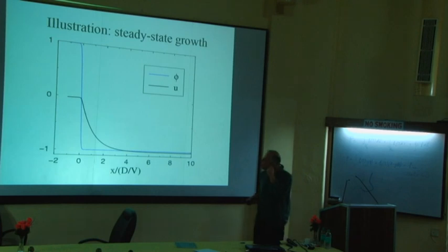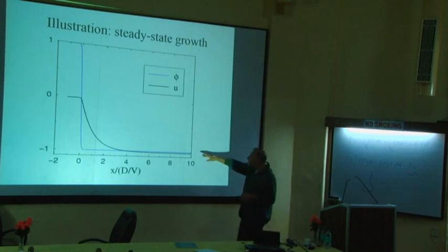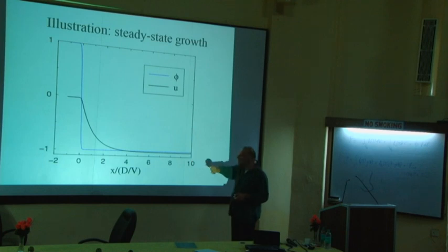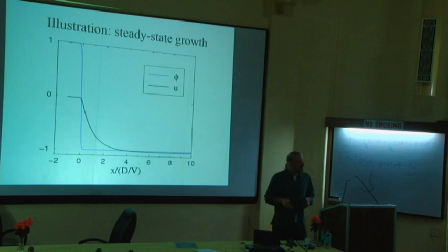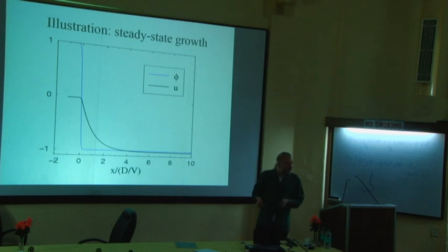So this is just a one-dimensional problem. You have an interface that is advancing, and if this advances in a melt that is undercooled enough, that is where U goes to a value that is below -1 far away from the interface, then you can quite easily show that there is a steady state solution. In this case you can exactly solve the sharp interface problem.